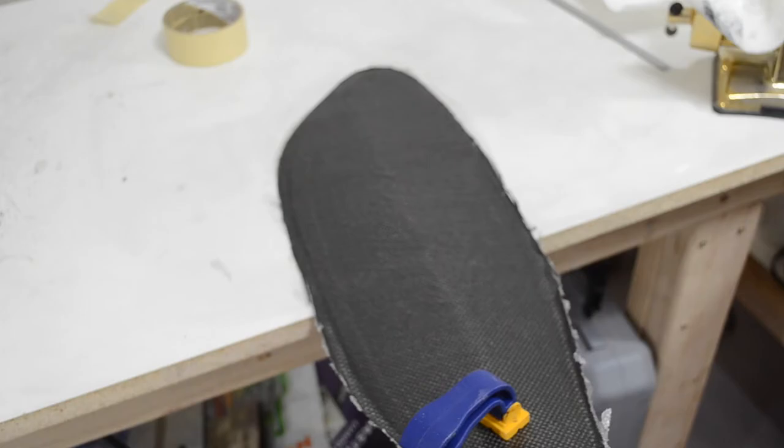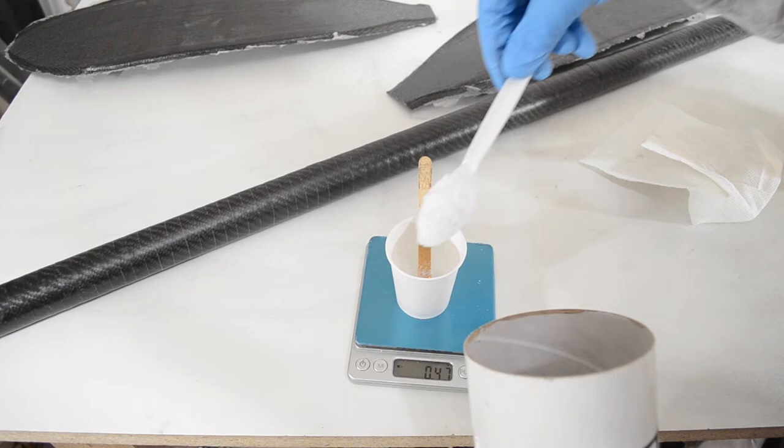To make sure I got that, I clamped the blades onto the shaft and laid it across two different table tops, and then just saw if it wiggled at all. It wiggled just a little bit so I sanded a little bit more until it was flat and ready for bonding. I bond prepped the paddle by sanding it and then wiping it with some alcohol. Then I mixed up a batch of epoxy thickened with colloidal silica.